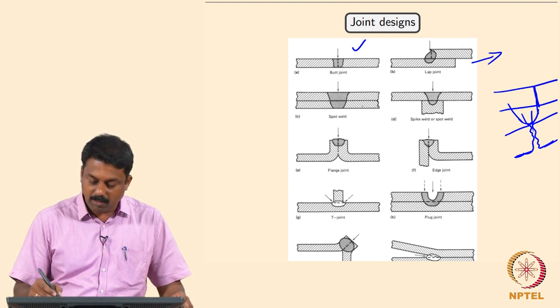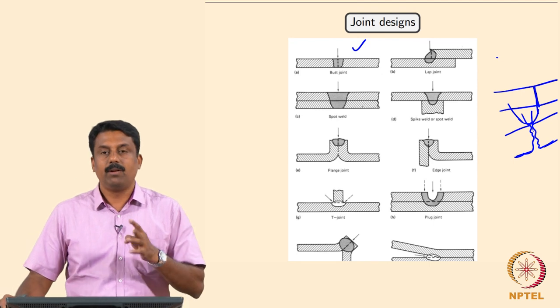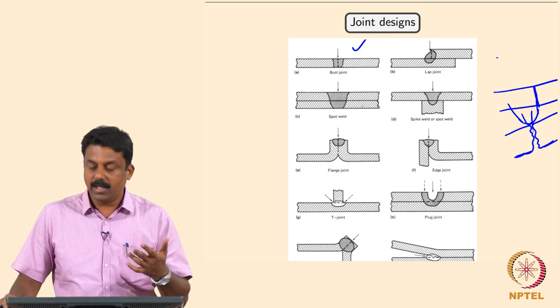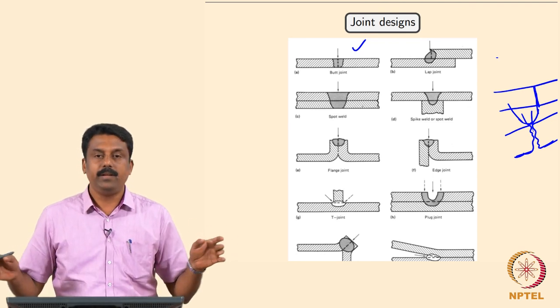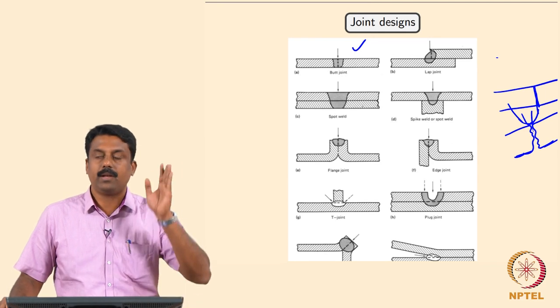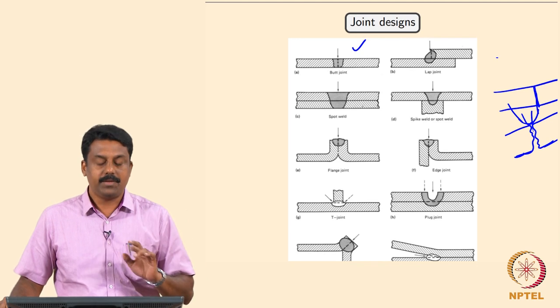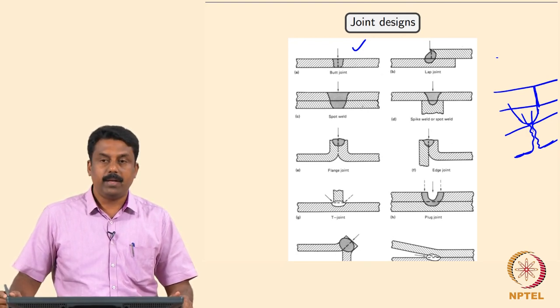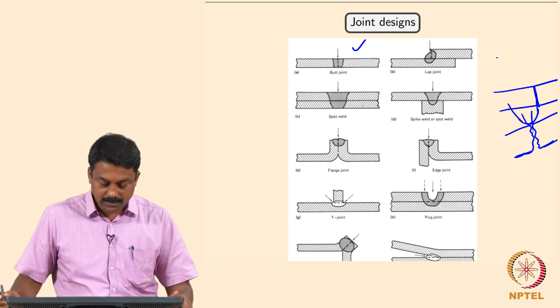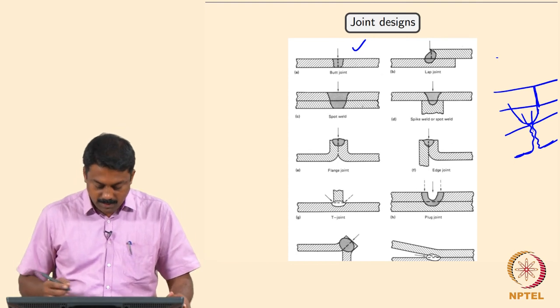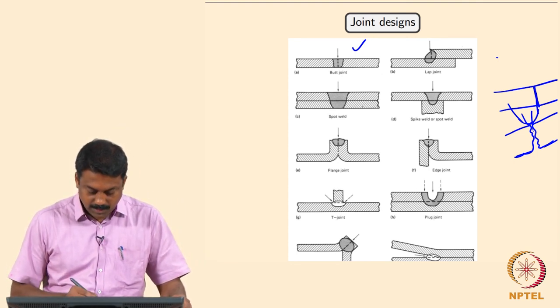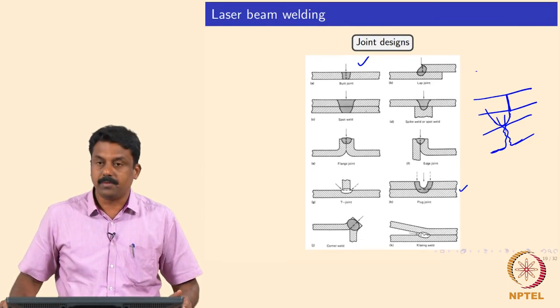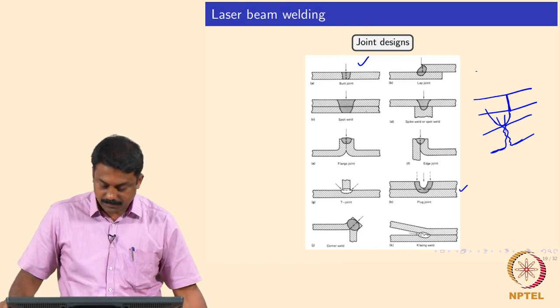Because of that, overlap configuration - lap welding - is advisable. We can go away with that edge preparation problem. That is why in automotive industries laser welding is mostly done in overlap configuration. Otherwise if you are using a very long thick sheet, edge preparation is very tricky since shearing can leave surface variation. In overlap configuration it is very straightforward. Laser spot welds are also widely used and for some applications, instead of using a seam weld, you can use laser spot welds to reduce weld area. Various configurations like plug joints and corner welds are also commonly used joint designs for laser welding.